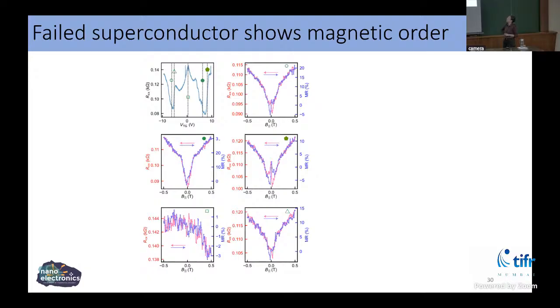Interestingly enough, I also stumbled across a device which was a failed superconductor. What do I mean by a failed superconductor? It means that I got the characteristic dip that I usually see in my devices, but this dip did not go to zero resistance, which means that it could have been a superconductor and it was not. Even in this device, when I looked at the neighboring points of the regions that could have been a superconductor, I did find some amount of hysteresis. This particular plot does not have any hysteresis, and it's in the middle, not near the superconducting part. So when I get such devices, which probably have an angle off, I did not get superconductivity, but I still have that magnetic order.